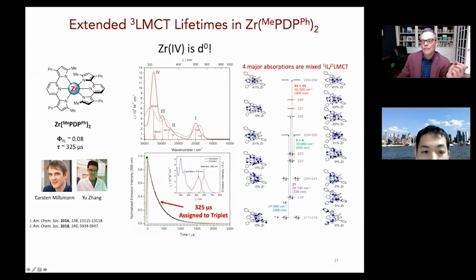But in some of the other ones, this has no zirconium character and it's all ligand centered. So there's this mixture of ligand to metal charge transfer in conjunction with ligand centered character. And I think it's those two things that really conspire to give you these really interesting excited state properties. Because it's not typical that you see TADF in a lot of molecules. And it's even stranger that this is, I think, the first example in a ligand to metal charge transfer compound. So it's got all of these interesting characteristics, but then it has that ridiculous excited state lifetime. I see. And I don't think on paper you could have predicted any of this.